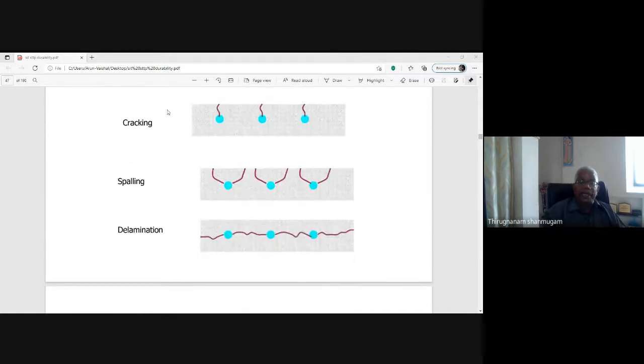There is another schematic diagram. This is the reinforcement. Cracks have formed from the reinforcement to the surface of the concrete, and via these cracks, oxygen, water, carbon dioxide, chloride ions, etc., are penetrating, and this causes rusting around the steel reinforcement, and the volume of the steel reinforcement increases further and further. So spalling of the cover concrete takes place, because the increase in volume is about 6 times.